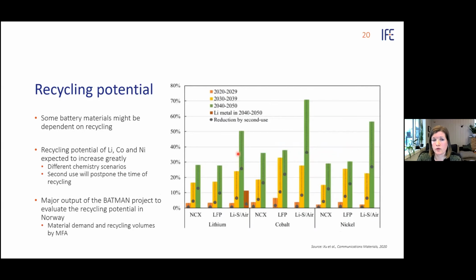And if we go more into the potential of recycling, this is a figure looking at lithium, cobalt and nickel in the 2020s, 2030s, and 2040s, and what the potential for recycling would be. Again, I'm focusing on the NCX scenario, the most likely one, with NMC and NCA cathodes. We see that for lithium we could have almost 30% recycling, for cobalt about 35%, and for nickel almost 30% recycling rates in the 2040s.